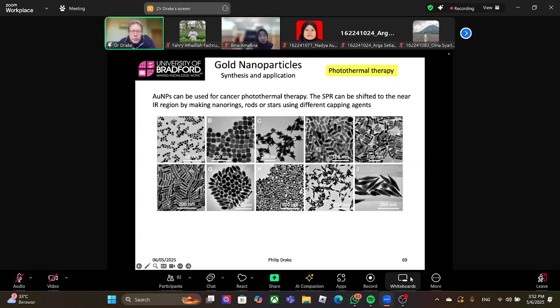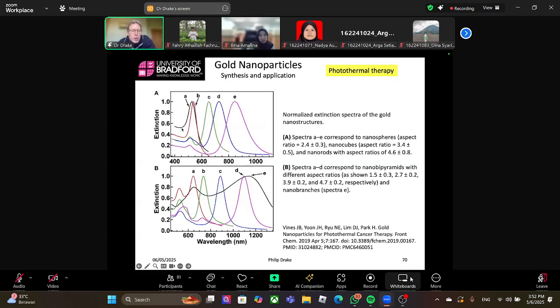When you change the surface of the gold, the shape of the gold, you change the SPR resonance, and you can make it shift down to the infrared region. So standard gold particles have the SPR peak around 500 to 600 nanometers. As you make nanorods, you get a new SPR peak occurring down at 900 nanometers. So this is now in the near infrared region and becomes a very strong absorber. So we can use a near infrared laser to excite this resonance peak within the living structures, and that produces thermal heat inside tumors.